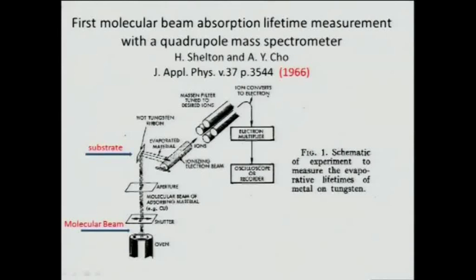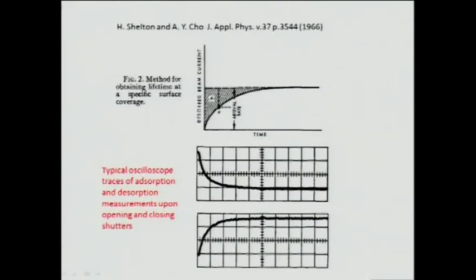And then the typical trace we saw when we open and close the shutter in that experiment: you see, when we open the shutter, we see the exponential increase in the signal, and then it saturates at the equilibrium time because the adsorption and desorption rates are equal. And then when we close the shutter, we have desorption from the surface, and then reach equilibrium. This shaded area means the equilibrium surface coverage of atoms on the surface at that temperature.